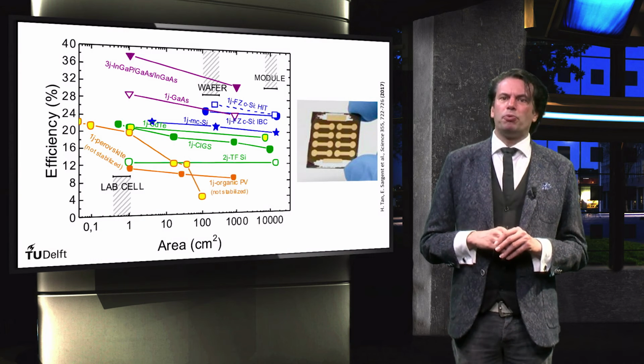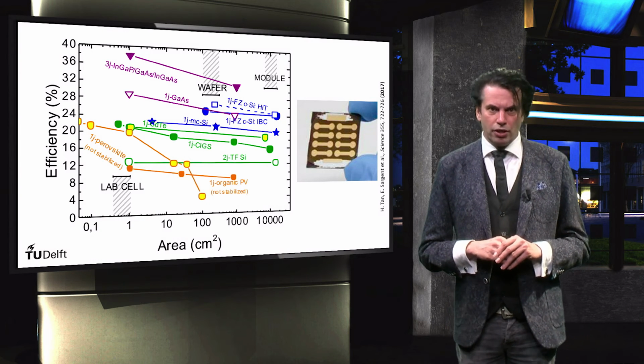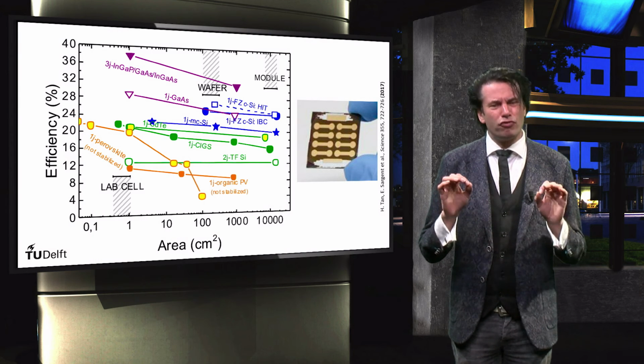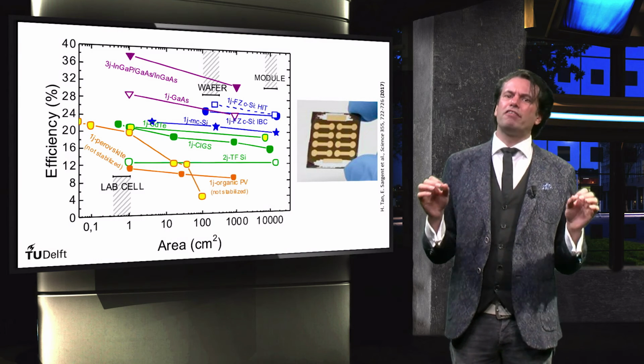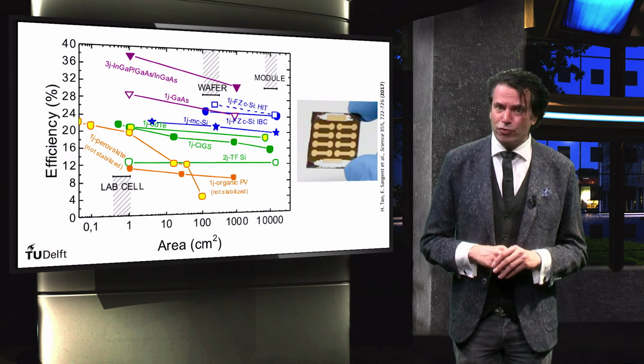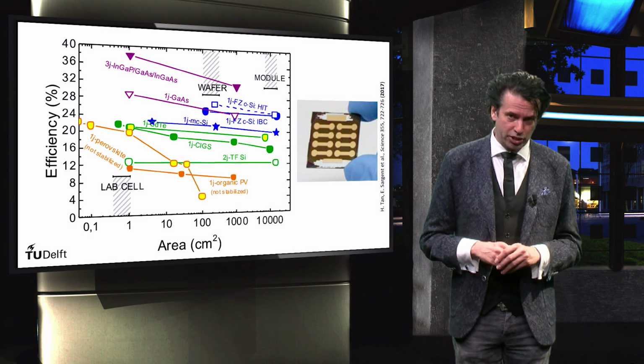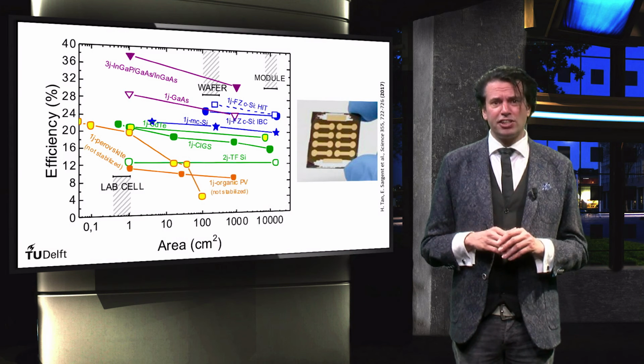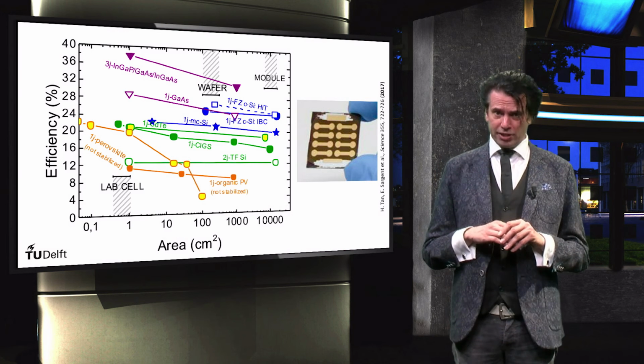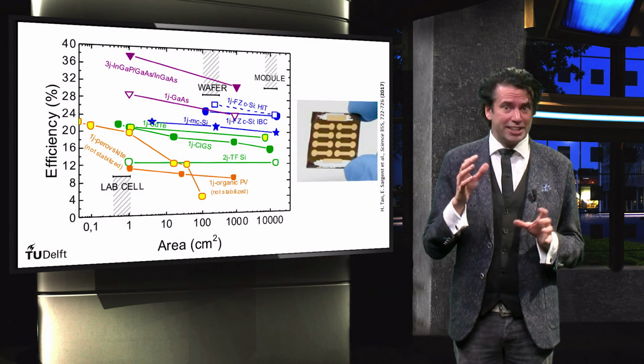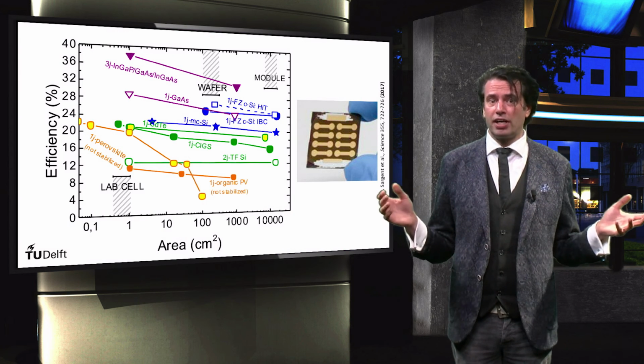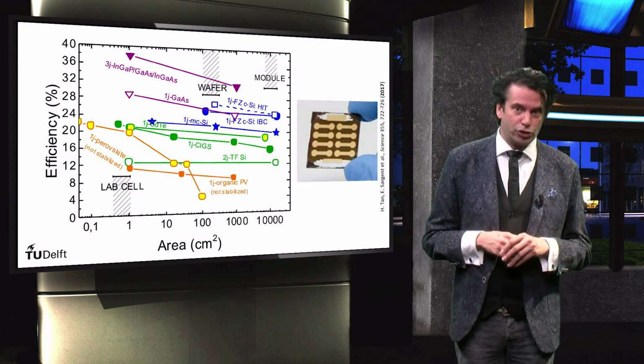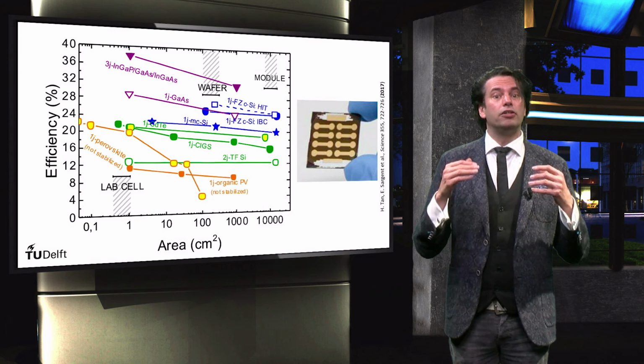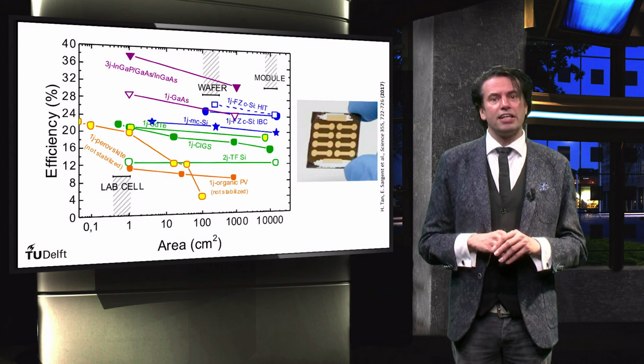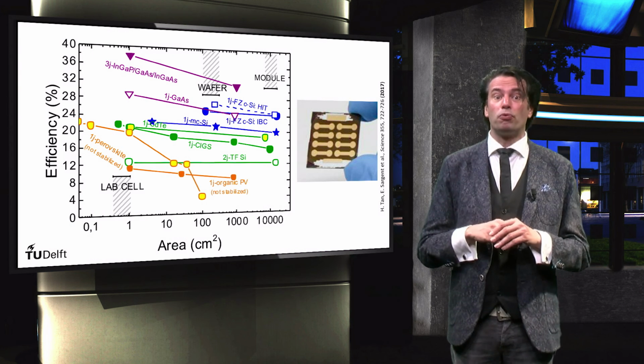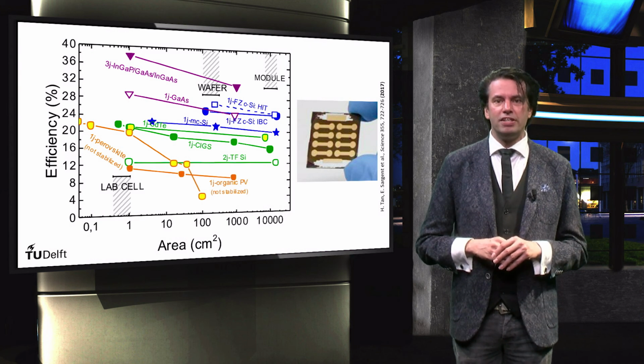The other line is corresponding to the perovskite technologies, which shows that this technology is far from mature yet. Record efficiencies above 20% have been obtained for cells with a size smaller than 1 square centimeter. The conversion efficiencies are drastically reduced when the size of the perovskite cell is scaled up with a factor of only 10 or 100. In addition, the perovskite technology suffers from instability issues as well. The performance degrades in time. So perovskite PV technology still faces significant challenges to prove that it can become a mature PV technology in the future.